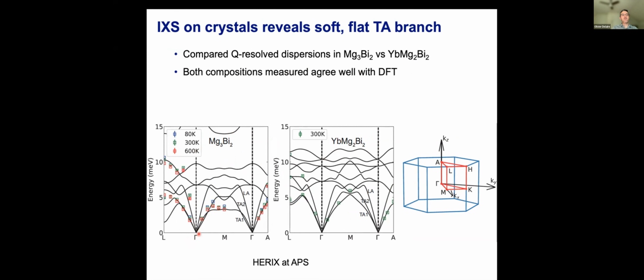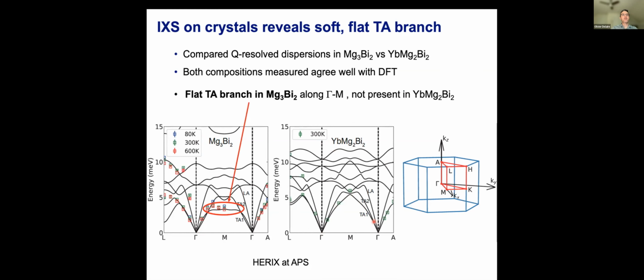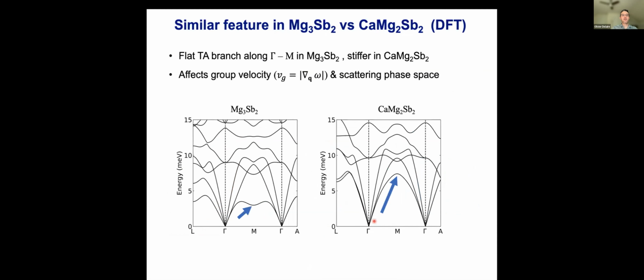And what we find is that when you look at the binary, so magnesium being on both sides, 1 and 2, you find a very soft transverse acoustic phonon branch. And when you substitute the magnesium 1 with ytterbium, which is much heavier here, you actually find a stiffening that's quite pronounced for this TA branch. And so this is really the origin of the modulation of the thermal conductivity. We see that in the antimonides as well.